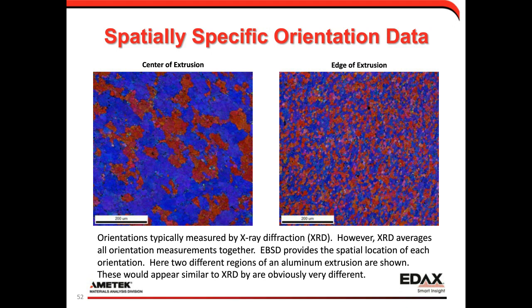So this is just an idea. These are two sections from different areas of an aluminum extrusion. We look at the orientation map on the left from the center, and then from the edge of the extrusion on the right. You can see they have two strong extrusion components: a blue 111 and a red 100 component. The one on the right has a similar red-blue distribution.